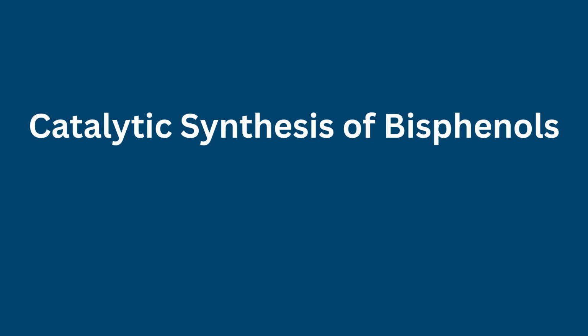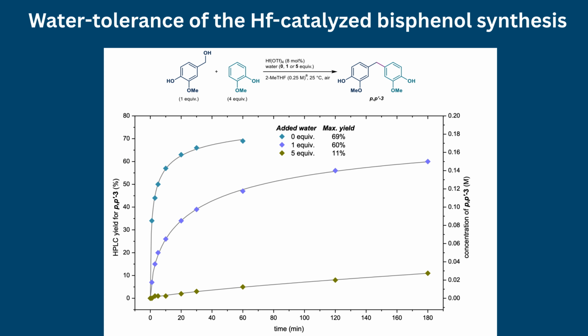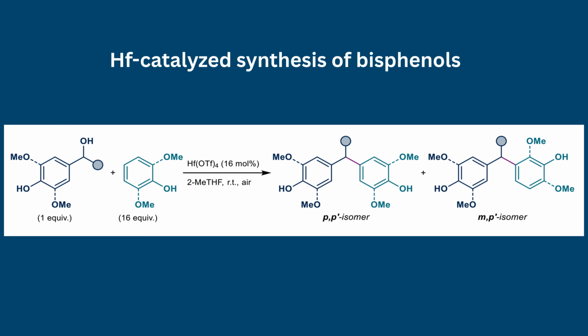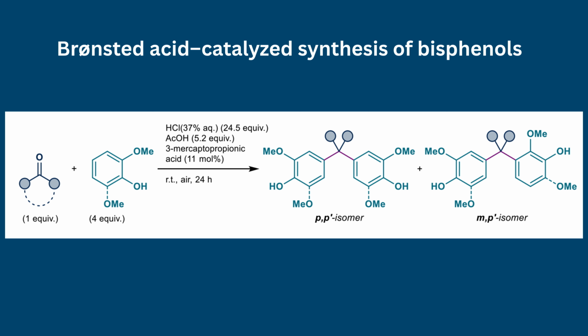Catalytic synthesis of bisphenols. Selected candidates were synthesized using environmentally benign catalytic strategies. Two primary routes were employed. Lewis acid catalysis: moisture-tolerant zirconium or hafnium catalysts enabled Friedel-Crafts-type alkylation of benzylic alcohols with electron-rich arenes under near-ambient conditions. This approach minimized energy input and eliminated the need for stoichiometric dehydrating agents, producing water as the sole byproduct.